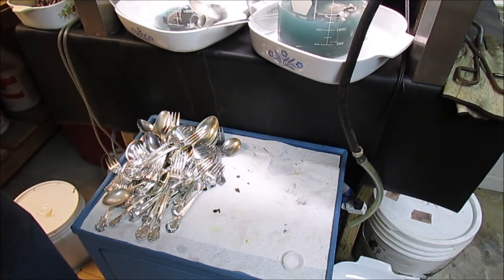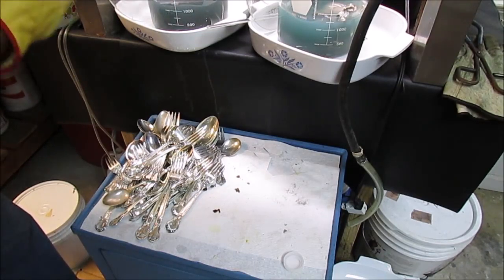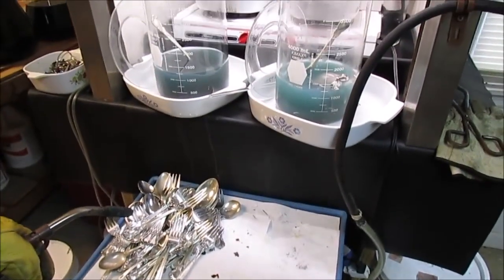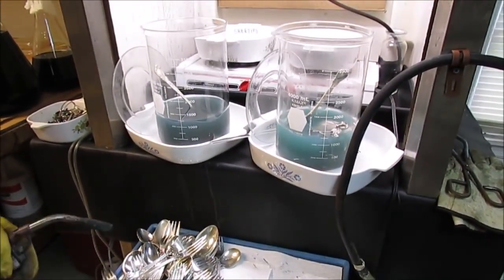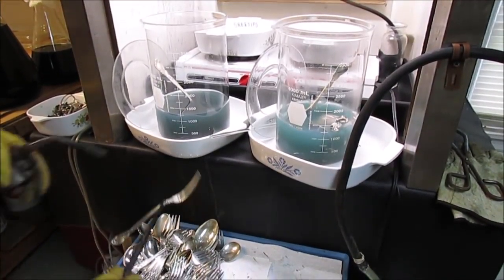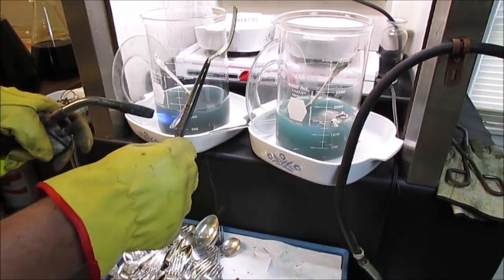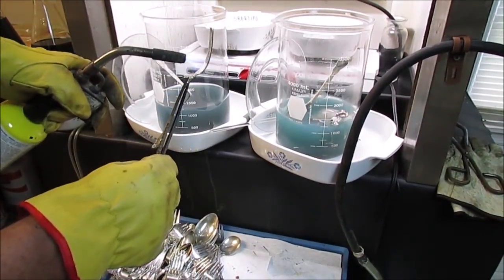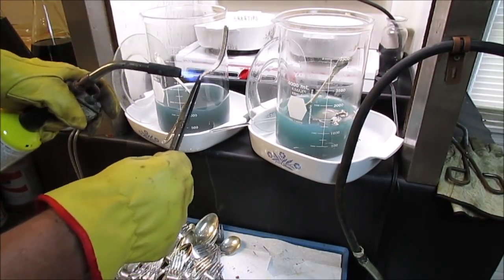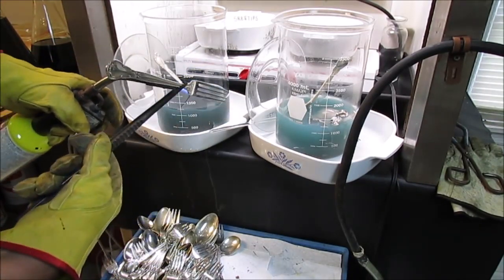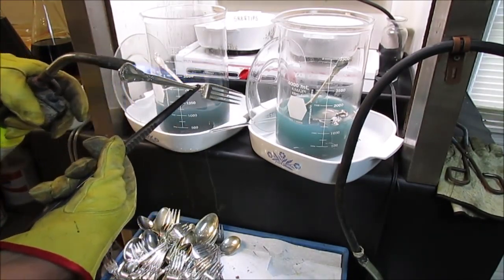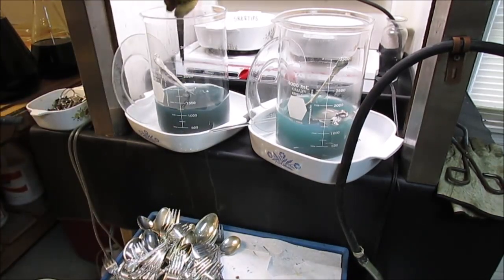And then what we're going to do is start adding some of this flatware to these beakers so we can start dissolving the flatware. Now I'm going to start burning these pieces of flatware down here. These aren't going to be as bad as the sterling silver items. You shouldn't have to heat them to redness. Just heat them up a little bit to burn off any kind of oils or junk that might be on there, and then add it to the beaker.